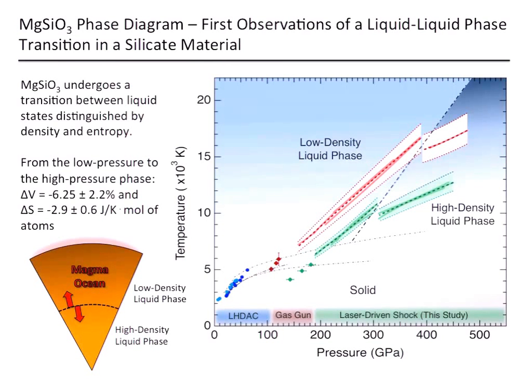So if we do similar experiments with different initial densities, we trace different paths in pressure-temperature space. And we see that same kind of discontinuity in the thermal emission and the velocity in both polymorphs, but in the glass, it occurs at much, much higher temperatures and pressures. So we believe we're seeing the same transition in both materials.